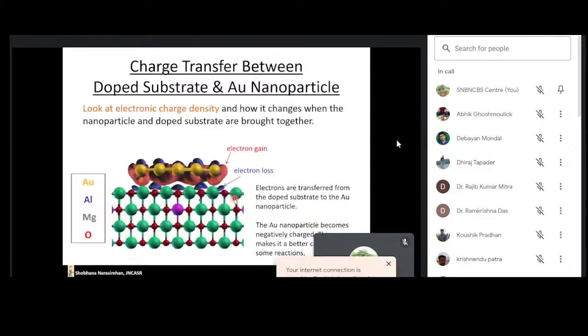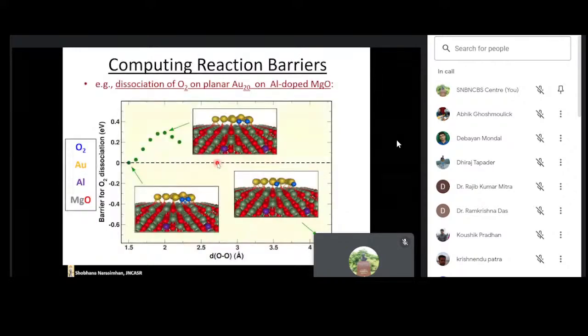So what happens, just like in the cobalt phthalocyanine case, once again, you have these red lobes showing charge being gained by the cluster. It has been lost by the support and it is transferred to this nanoparticle, which then flattens out. Now, this charged cluster, there is reason to believe that it will also be a better catalyst for certain reactions. So we can check that.